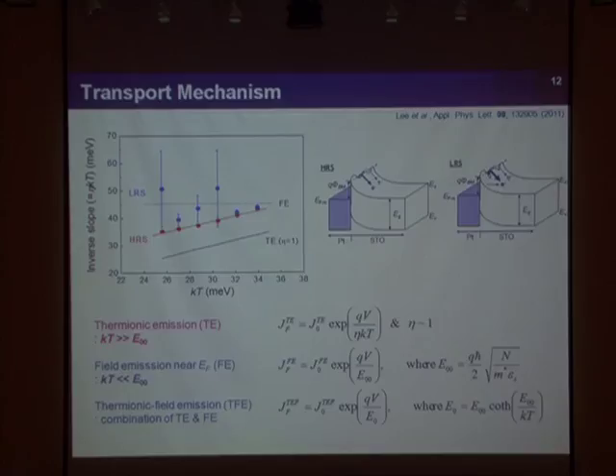So from all these results, I can propose this kind of cartoon to explain the mechanism. In both HRS and LRS, the barrier height doesn't change quite a lot. However, in the LRS case, tunneling transport is somehow allowed, probably due to a very local area of barrier height lowering or depletion width change. So this is the picture we can propose to explain the switching behaviors of SrTiO3 Schottky junctions.